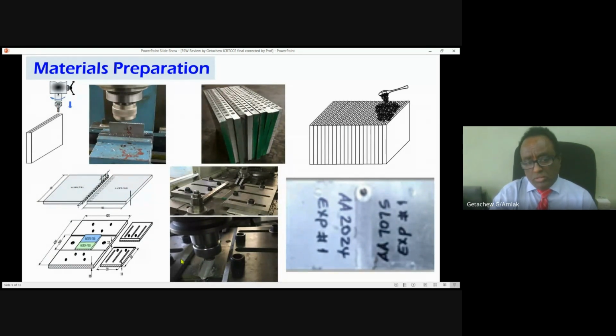One of the critical starts for this process is material preparation. In order to introduce the alumina powder into the material, the volume percentage has to be calculated. For this particular case, 8 volume percentage is the critical and appropriate quantity. For that, the number of holes has to be computed. In this case, 15 holes of limited size have to be provided on each edge, and accordingly this has been made ready for inclusion of powder. You can see how powder is being incorporated in the hole.